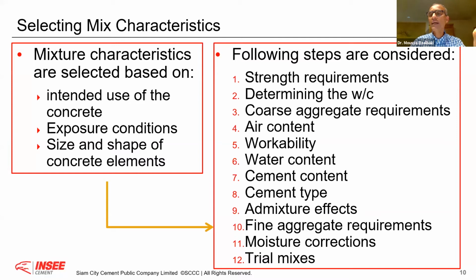After, the coarse aggregate. You see, coarse aggregate is not inert. Coarse aggregate plays a very important physical role in the concrete, because coarse aggregate will occupy a big volume of your concrete. Almost, I would say, 40% of the volume will be occupied, even sometimes more, by the coarse aggregate. After, the air content, because concrete can be with entrained air or without entrained air. In Sri Lanka, we do not entrain air, we have entrapped air. But if you go to a country like Switzerland, because we have winter, we need to protect concrete from frost. Therefore, we engineer it. Therefore, this topic we will not discuss here. The workability, which slump I need. I'm going to pump the concrete, I'm going to shovel it, I'm going to bring it with a crane. That is all an important aspect.